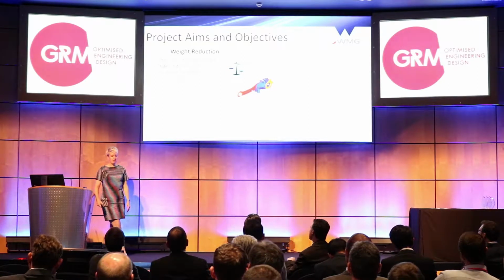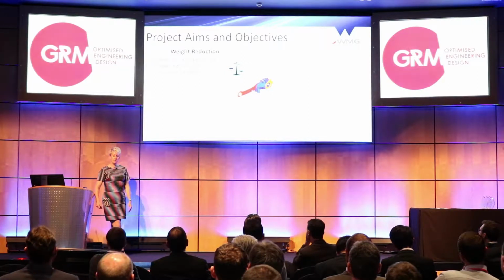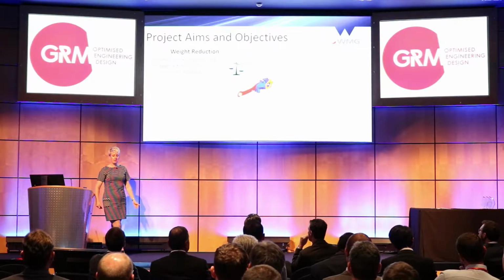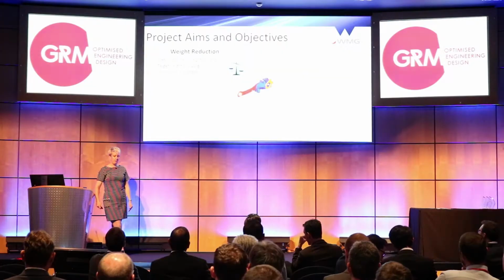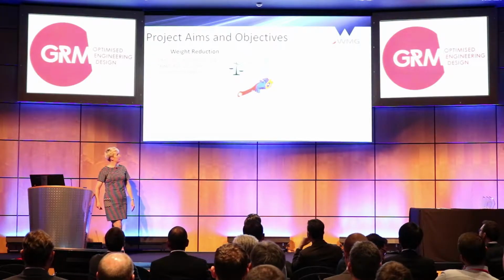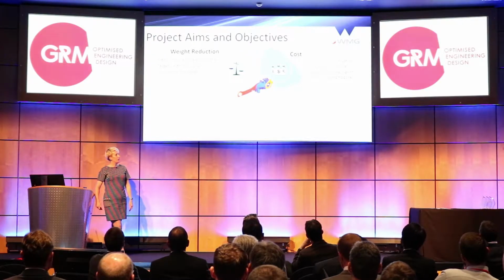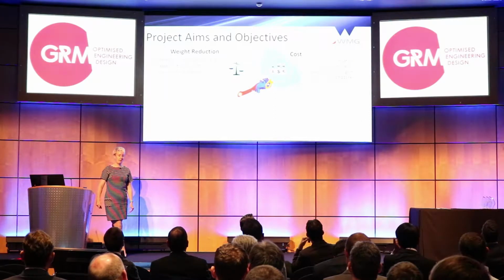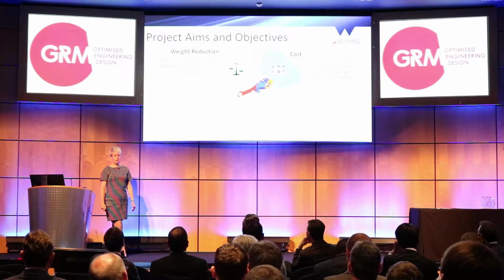So one area is weight reduction. The original steel component was over 6 kilograms, and we wanted to get down to 3.15 kilograms, which would be a 49% saving. Secondly, it's cost. We understand there is going to be a cost increase with using composite materials, and the target set by Ford was $30 per vehicle.